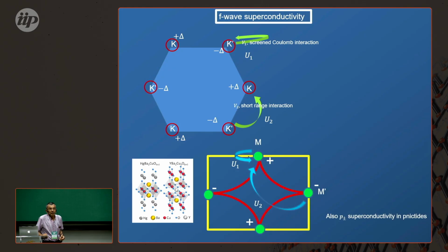A similar argument applies to the cuprates, giving d-wave superconductivity. There are two hotspots, the two Van Hove singularities, and if the inter-hotspot interaction is stronger than the intra-hotspot interaction, you will always get superconductivity.